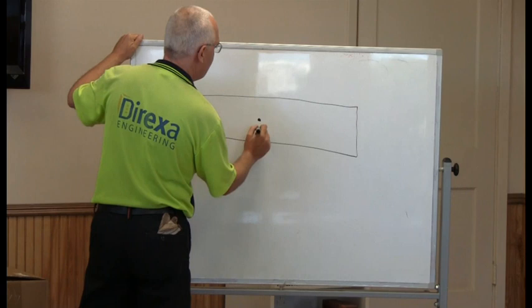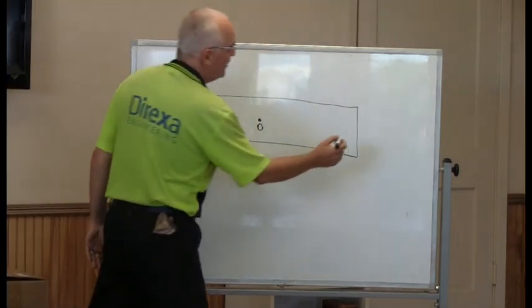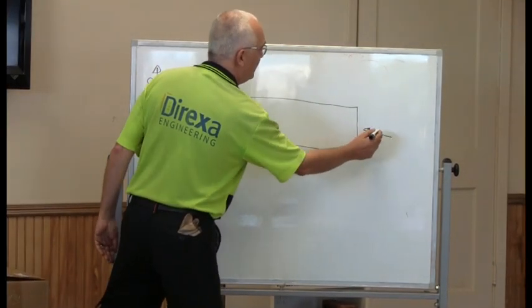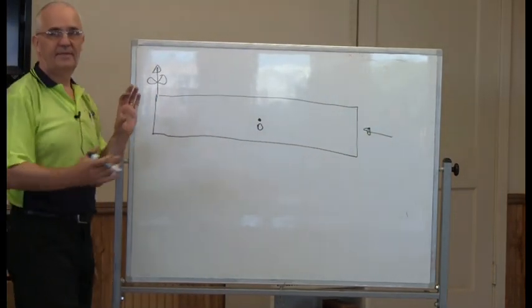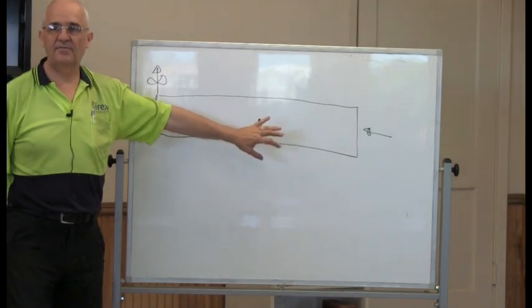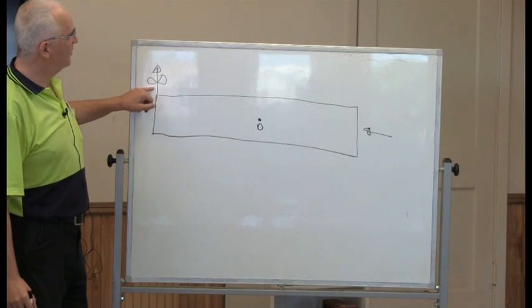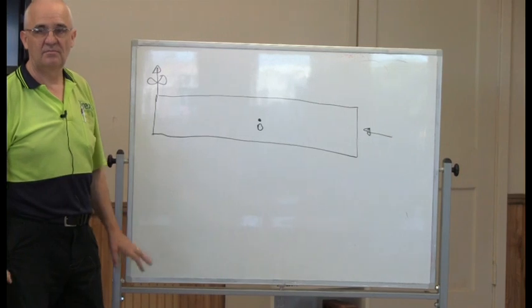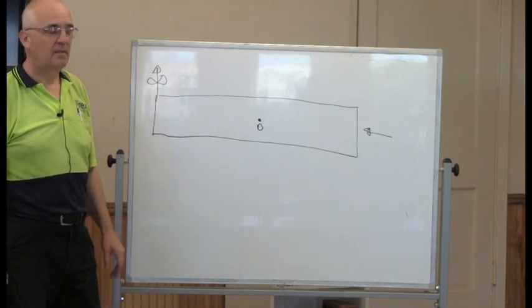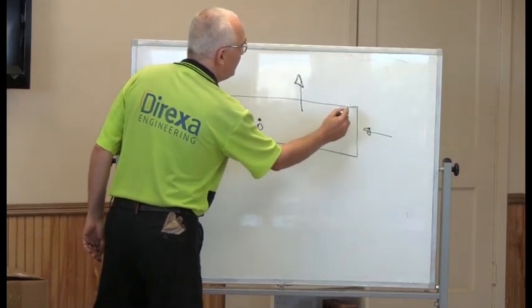And I measure here a pressure, and I measure zero inch of water column. This is open. I have an airflow coming in, and in that spot, I have zero. That's a guide: if I speed up my fan, my zero spot is going to change. Okay, that's fine. When you have this system, and we're going to make it really simple,